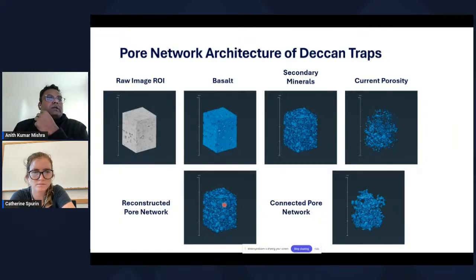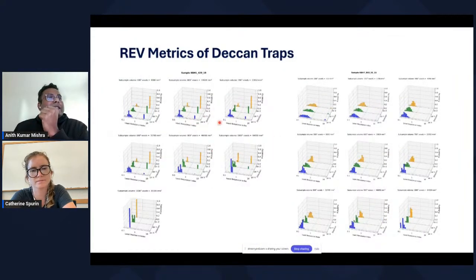But when we reconstructed the porosity by combining the secondary minerals with the current porosity, we found some connected pore network. And this connectivity has been utilized for the REV analysis for the Deccan. For the REV analysis for the Deccan, the trend is still the same, that the convergence started to happen at 1000 cubic voxels. So basically, we still need a very large sample size to come up with some sort of confidence to say, okay, this is the REV for the basalt, and this is what the basalt looks like, and this is what would represent the field scale scenario, and can now be representative of the storage capacity as well.